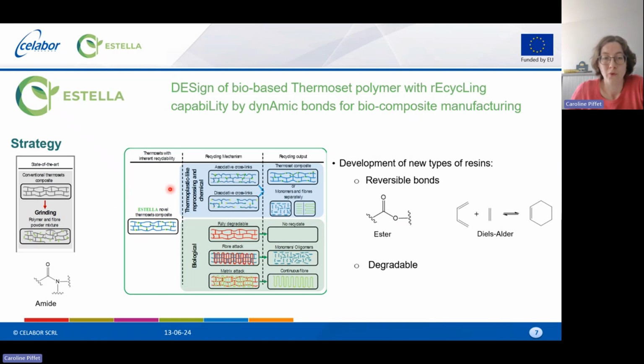So first, for the recycling mechanism, we developed some resins that can be simply destroyed by reversible links between the precursors. And so the reversible thermoset composite can be remolded, or we can collect the monomers and the reinforcement fibers separately, depending on the precursors that are used.